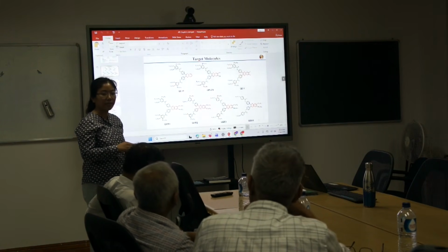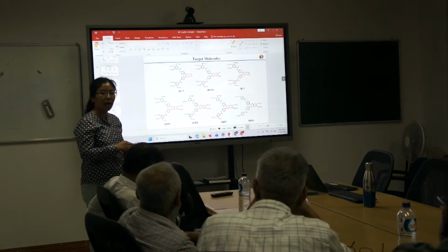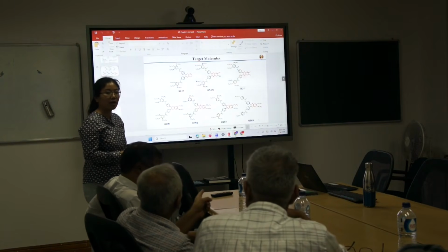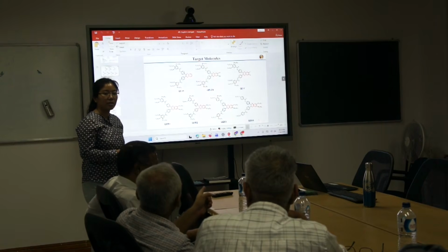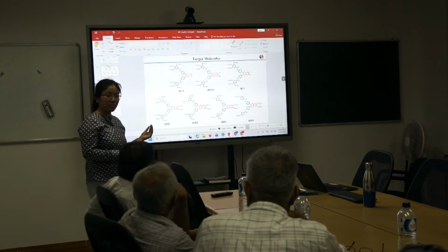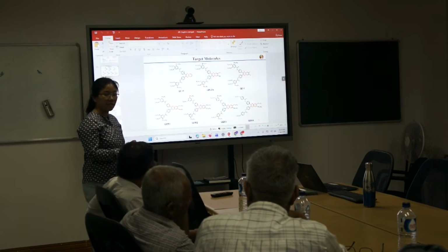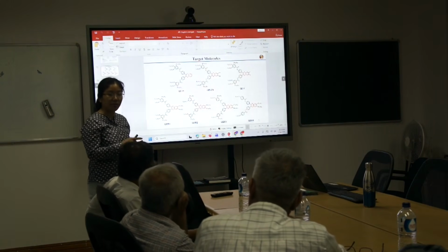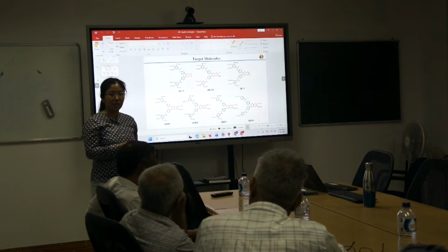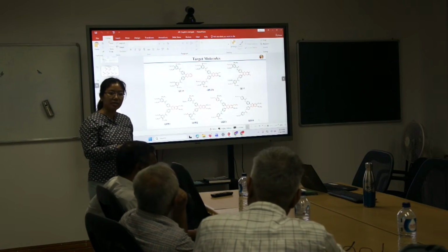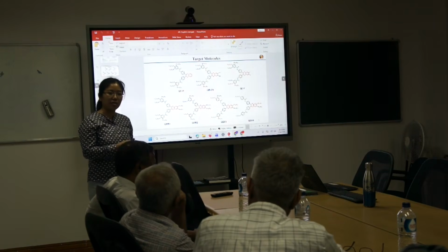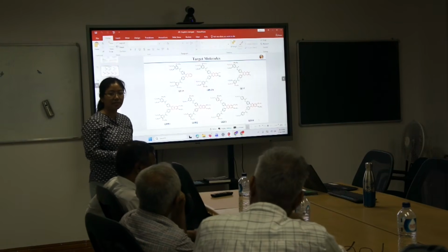Yeah. So what I was asking is, do you do that experiment twice to verify? Yes. That's the answer. And also DSC, how many times do you do DSC? How many cycles of DSC do you do? Yes, sir. After POM study, we check the DSC. In DSC we can see the phase transition temperature. We do 2 cycles, and the graph that we plot is the first cooling and the second cooling.